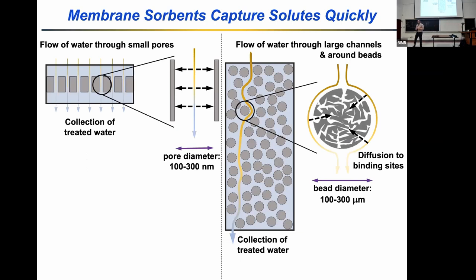And we're gonna talk about membrane adsorbers today. And the idea is we're gonna make a membrane adsorber that can selectively grab heavy metal ion contamination out of drinking water. And the argument for membrane adsorbers is that they have very fast response times or short diffusion times. I could compare a membrane adsorber to a traditional packed bed, and for the packed bed, for the solute to get from the flowing solution to the binding sites, it's got to diffuse over a characteristic distance that's the diameter of the resin, right? So typically 100 to 300 micrometers in diameter. For the membranes that we're making, we'll have a characteristic distance of about 100 to 300 nanometers, and so much faster response times.